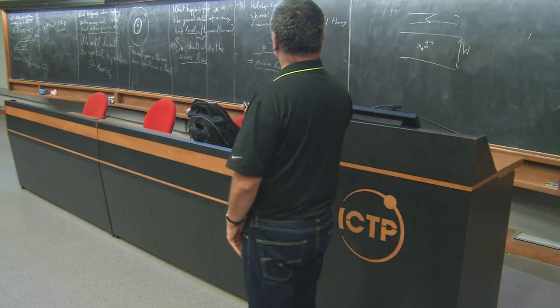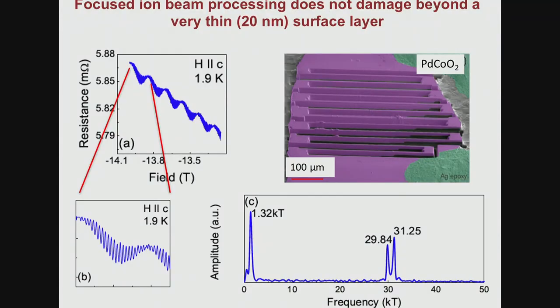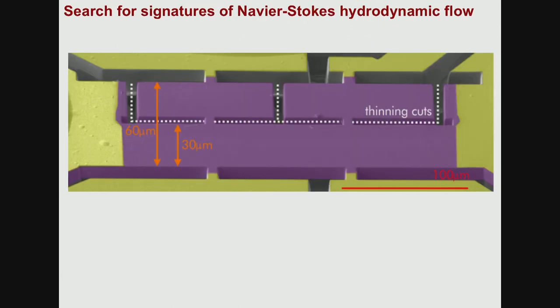The first thing we did was to take our crystals, this was about 6 years ago now, and Philip Moll sculpted them into meanders so that we could check whether we could see the Shubnikov-de Haas effect in them. The Shubnikov-de Haas effect is extremely purity sensitive. The question there was, could we do all this sculpting to those samples and leave them with a very long mean-free path? We now have 10 or 15 different ways of saying that we can do that. So then we just set out to do the simplest possible experiment.